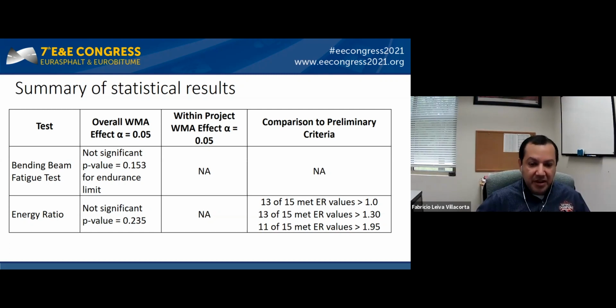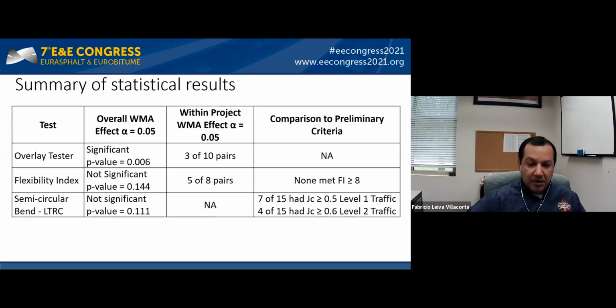The next test was the energy ratio. As well, we couldn't find any significant differences. And in that case, we do have some preliminary criteria to compare. And for most cases, all these warm mix technologies were able to be classified for medium to high traffic levels. And again, to show you the results that I discussed previously for the overlay, for the flexibility, those showed significant differences. Three out of 10 pairs for the overlay and five out of eight pairs outperform, or the warm mix technology outperform the hot mix technologies.